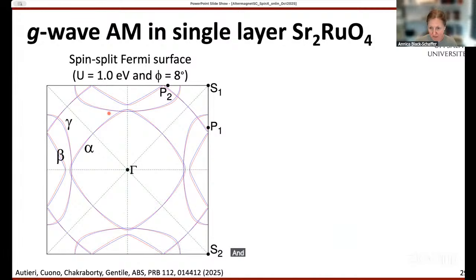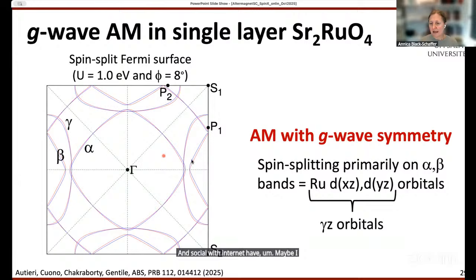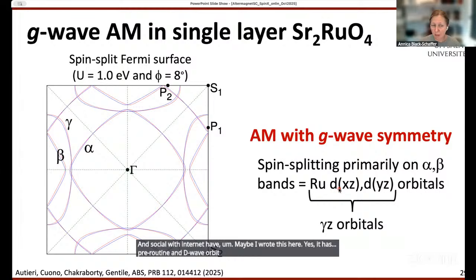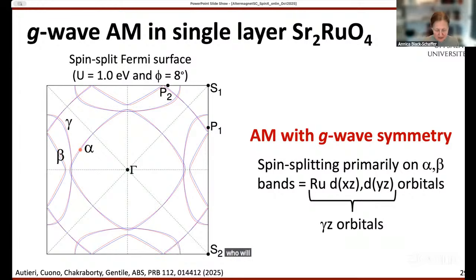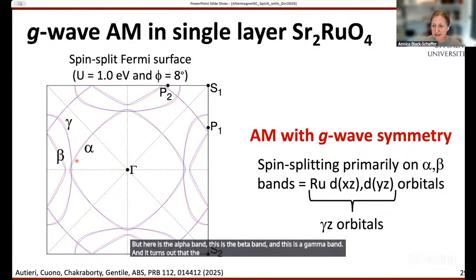Strontium ruthenate has, maybe I wrote this here, yes, it has 3 ruthenium d-wave orbitals. They form 3 bands, alpha, beta, and gamma. If you're used to looking at strontium ruthenate, this might be a little confusing, but that's because I have now extended my unit cell, so I had to fold my Brillouin zone. But here is the alpha band, this is the beta band, and this is the gamma band. And it turns out that the spin splitting is just sitting on the alpha and beta band. The one I get here on the gamma band is actually just sort of proximity induced from the other bands.